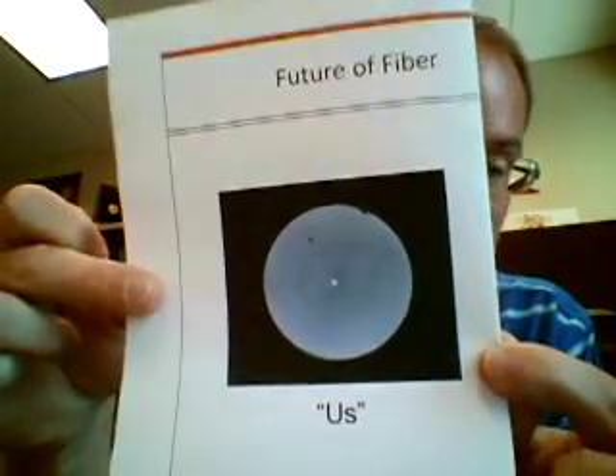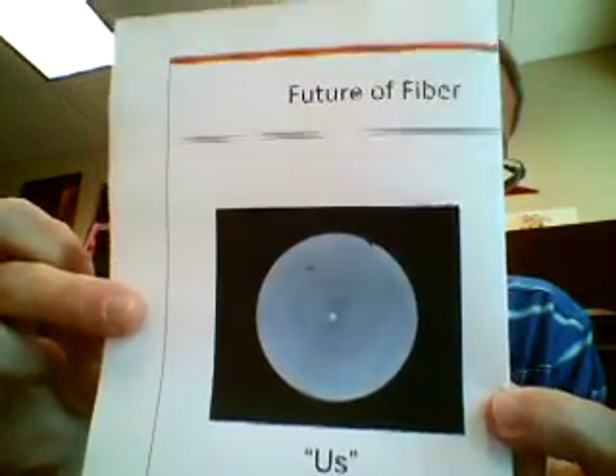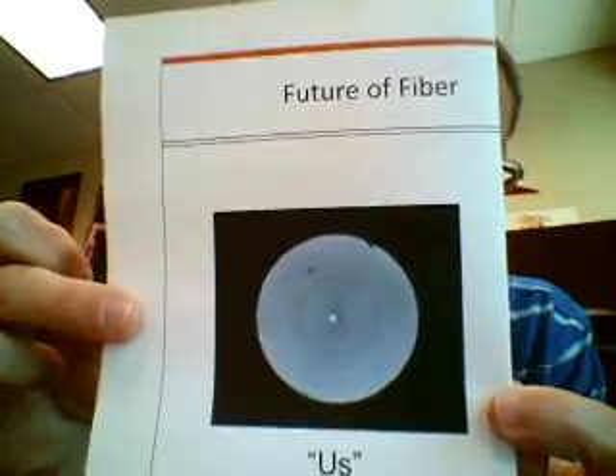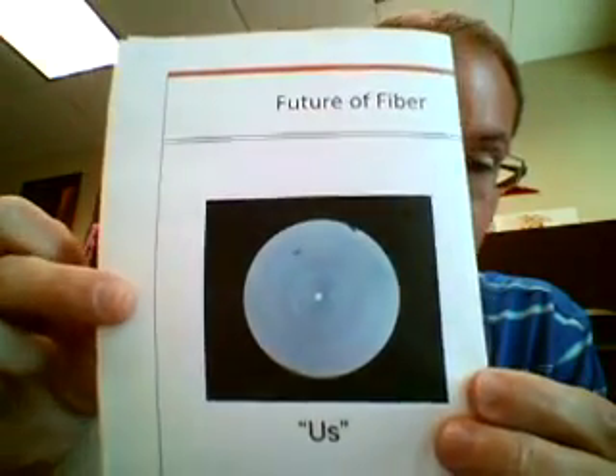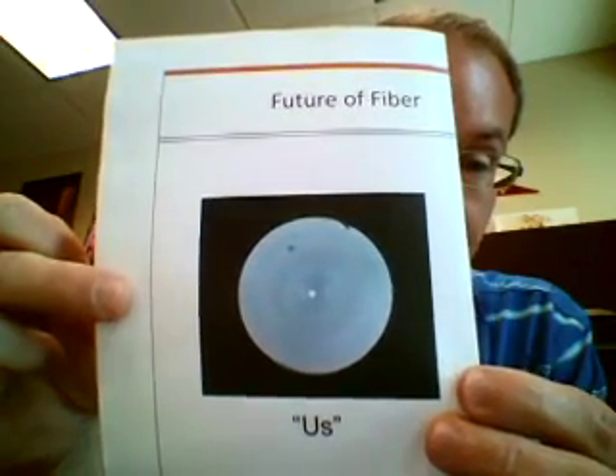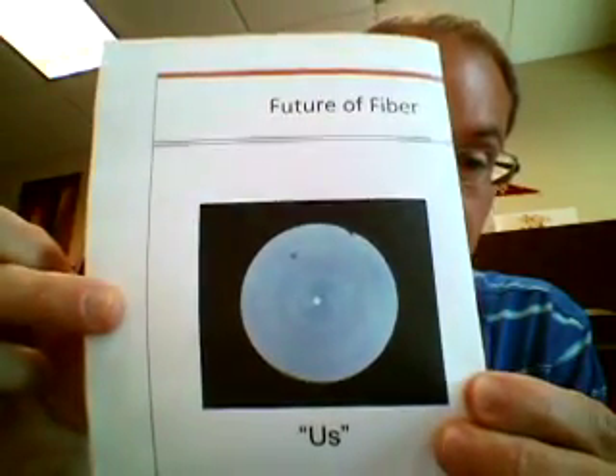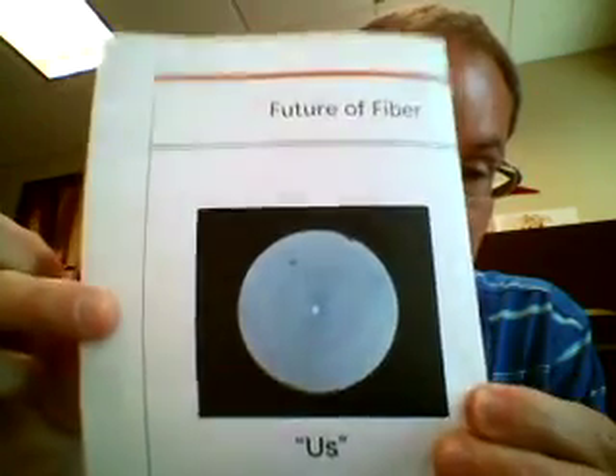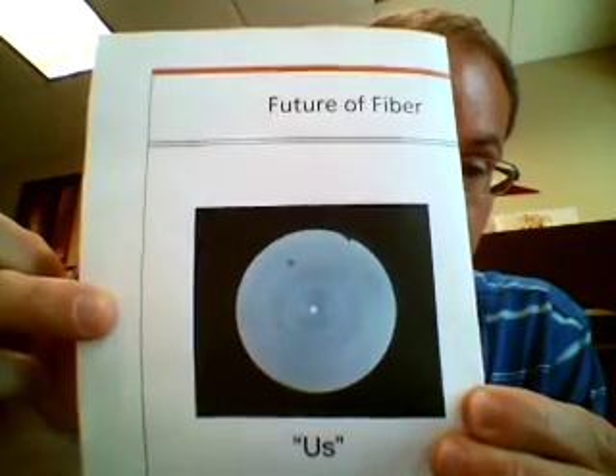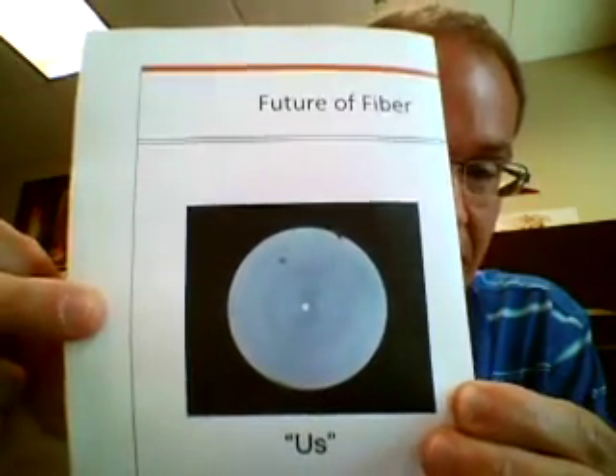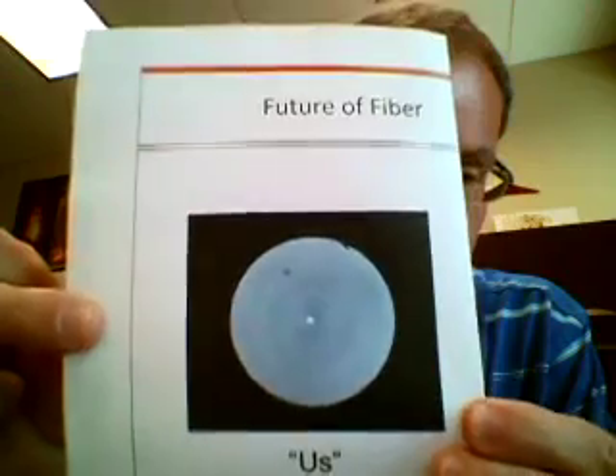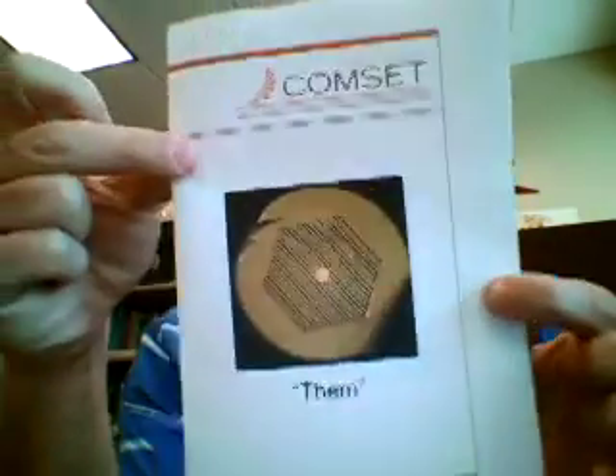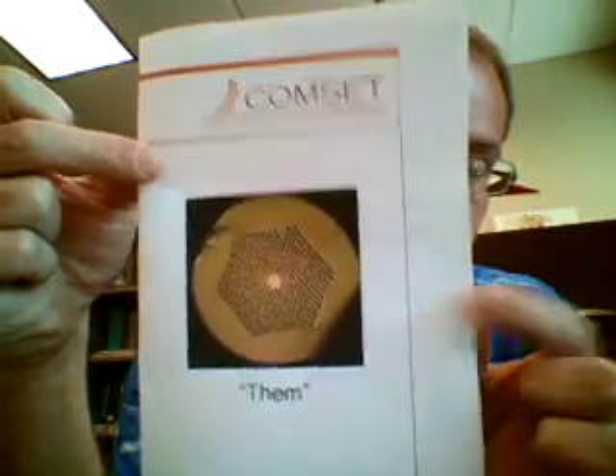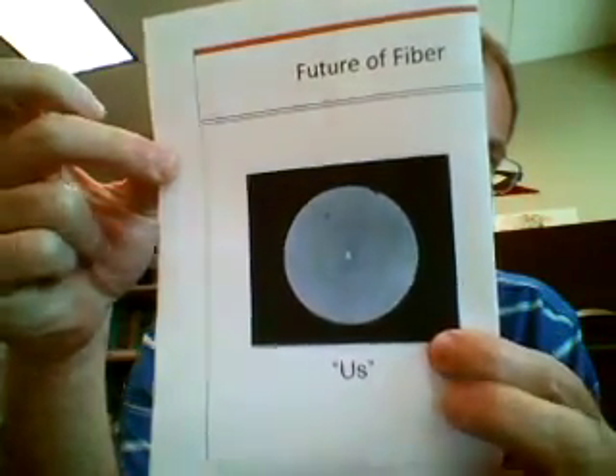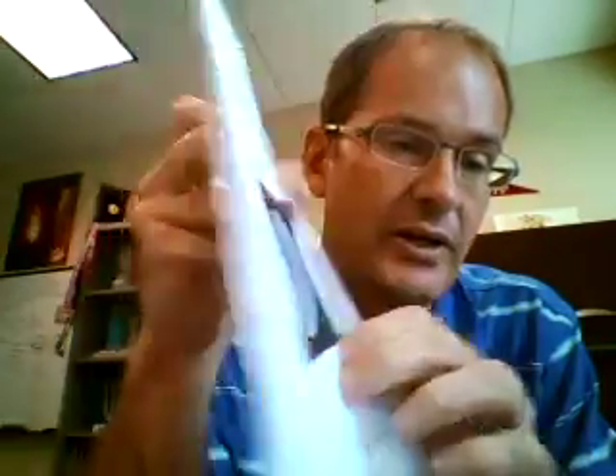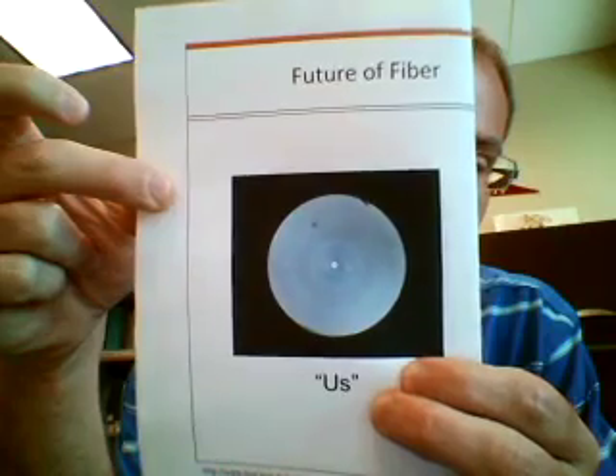So this looks just like a standard optical fiber, central core, homogeneous, large cladding, pure silica in that case, with a core that was derived from one of these molten core precursors. So this, in the cases of things like SBS, is much, much simpler, has fewer unit operations to manufacture, tastes like, forgive the pun, silica, behaves like silica, does everything that silica does, but it outperforms something that looks like that. So I would tend to favor making that any day over making that, especially when that has superior performance.